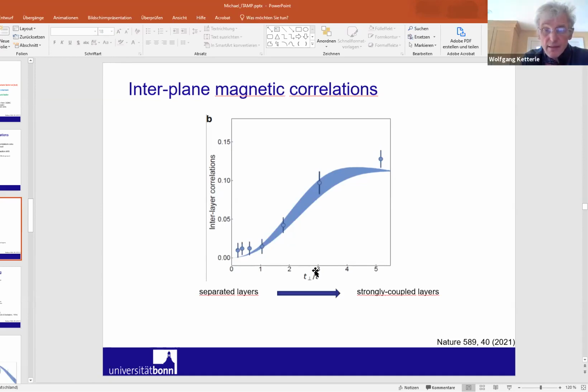I want to ask about the selection of the bilayer system. My understanding is you have a three-dimensional stack of pancakes. And now you want to single out a bilayer system, and this must be done with magnetic gradients and such. You explained before, if you have a stack of pancakes with a magnetic gradient, you can selectively image one of them. Yes. But how do you create your system of two layers which are coupled, embedded in all the other layers on top and the bottom? Okay.